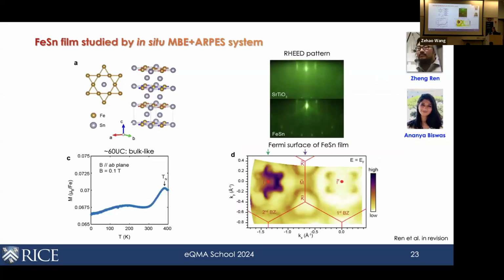To answer this, my postdoc, Zheng Ren, joined us about a year and a half ago, and then he brought with him his expertise in building an MBE system. So he built next to our ARPES chamber an MBE system where he successfully grew iron tin, Kagome iron tin, in thin films, and you can see the ordering temperature is bulk-like, and also this is a RHEED pattern, and also by this direct transfer from the MBE system to the ARPES system, we can directly measure the electronic structure without exposing this to air.